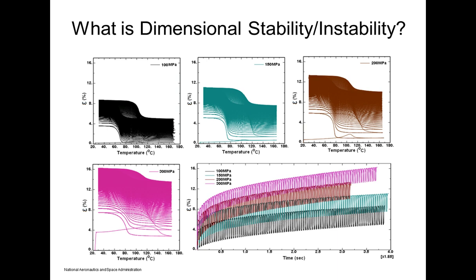Okay. Can you talk some more about the lifespan of nickel titanium after the stabilization? So in general, if we again stay away from high damage in the material, depending on how heavily the component is loaded dictates the lifing of the system. This is true in any shape memory alloy. The life of the system is dependent on how close to the limit surface of the transformation we're trying to drive the system. So, in other words, if the actuation system can generate 4% strain in a given condition, but we design the component to only have to deliver 2% strain, we can have hundreds of thousands or millions of cycles. And so with this process, that's one of the keys.